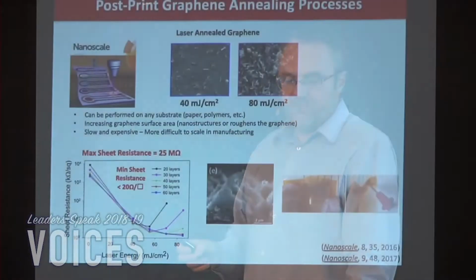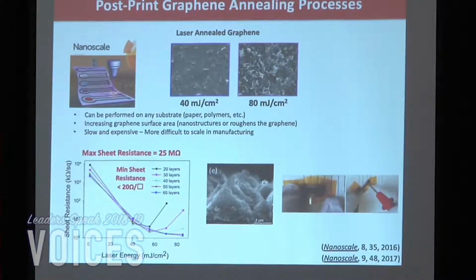So after you were to, let's say, inkjet print that graphene, aerosol print the graphene, or do this kind of spin coating technique, you notice that graphene layer, those graphene flakes, aren't really that conductive because still embedded in them to make them stick to that surface is an ethyl cellulose. It's a non-conductive binder. There's some solvents in there and so forth. So typically what researchers have to do is some sort of annealing process. And what's conventionally been done is thermal annealing, which is done at about 200 to 300 degrees Celsius. But of course you can imagine if you were to deposit or print that onto a paper substrate or a polymer, that's just going to burn up in that oven.